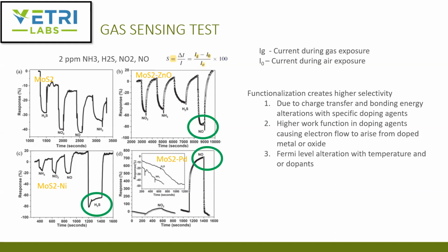For example, when you expose it to H2S, there could be a particular value, and then you subtract the air exposure, divide that, and that's your response that they're plotting here. So with hydrogen sulfide, it goes down to -30%, which implies that the current actually goes down, meaning the resistance goes up. The same thing happens with the nitric oxide, the nitrous oxide, and the ammonia as well. With the zinc oxide, there is signal. So all of these gas species adsorb and charge transfer in a similar way, except if you look at the nitric oxide, there is a clear separation in signature compared to the nitrous oxide, ammonia and the hydrogen sulfide.